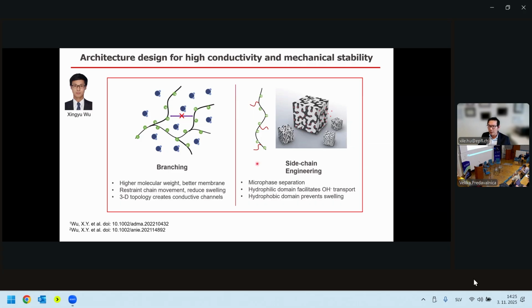The second approach takes advantage of sidechain engineering to make microphase separation. The idea is similar to Nafion, that you have in your polymer a hydrophobic and a hydrophilic part, okay? These parts of course will separate, and the hydrophilic part will facilitate hydroxide and water transport, while the hydrophobic domain prevents swelling and makes it stable. I will mostly talk about the branching approach.